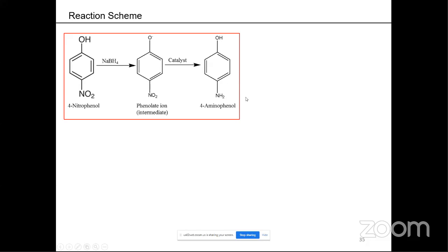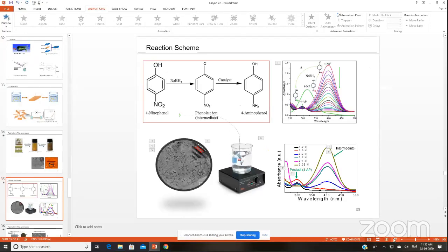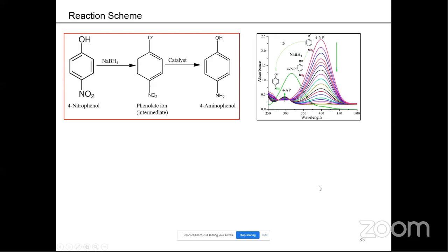We chose this reaction because it is a very simple reaction and can be characterized by using simple UV-visible spectroscopy. This large peak at around 400 nanometers is the peak for 4-nitrophenolate ions. The moment we put some catalyst into it, it goes to aminophenol, where this small peak appears. That means the disappearance of this peak represents the occurrence of the reaction.